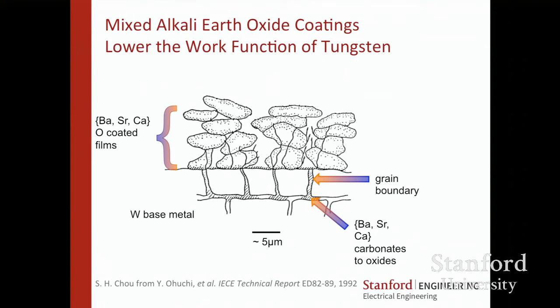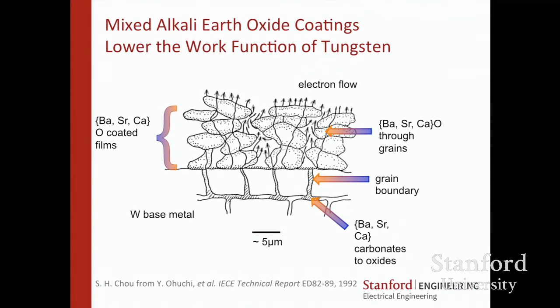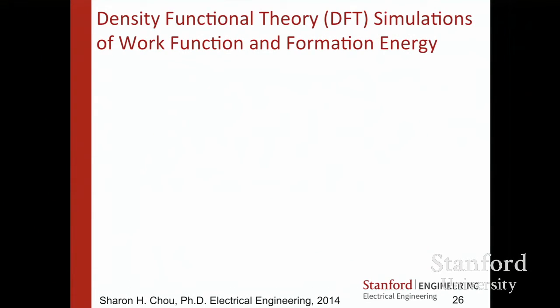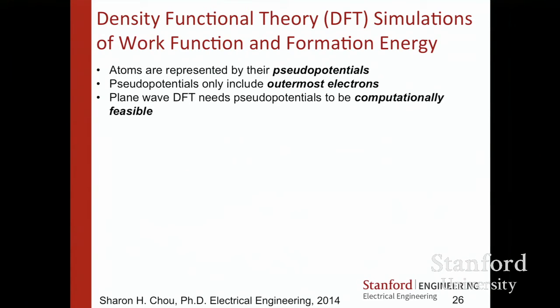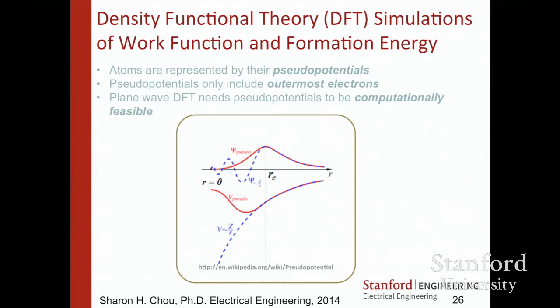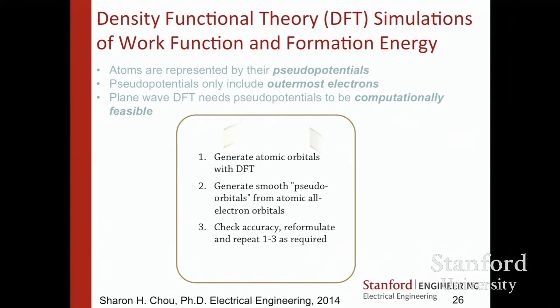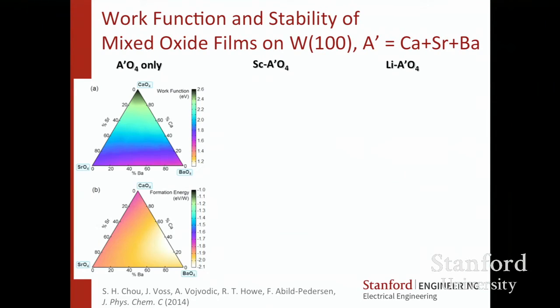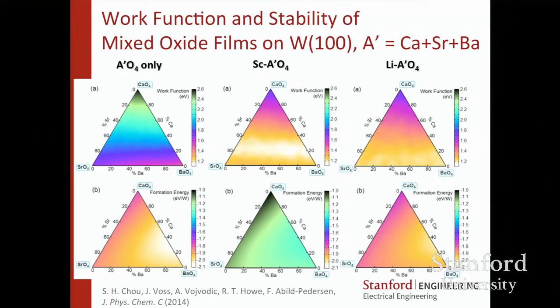In fact, in a polycrystalline case, you've got a lot of complex material transport and the electrons getting out of here. I'm just going to click through this because the shortcut is to compute it. Density functional theory is a standard way to, from first principles, not perfectly, but rather computationally efficiently, get the work function and the formation energy. And so with her diving in with Jens Nørskov in chemical engineering in a group at SLAC, she was able to gear up on this and adapt some code and end up using DFT, and there's some feedback loop of optimizing the pseudopotentials and all. There's some front work that's needed, but once you've got the machine set up, you are in business to do a whole bunch of calculations of work function and a proxy for formation energy.